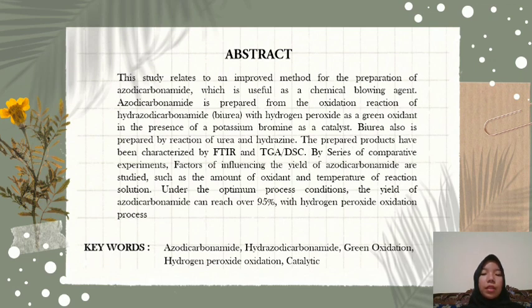Factors influencing the yield of azodicarbonamide are studied, such as the amount of oxidant and temperature of the reaction solution. Under the optimum process condition, the yield of azodicarbonamide can reach over 95% with the hydrogen peroxide oxidation process. And the keywords are azodicarbonamide, hydrazodicarbonamide, green oxidation, hydrogen peroxide oxidation, and catalyst.